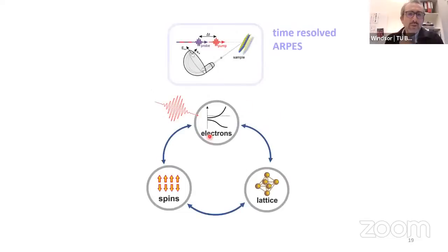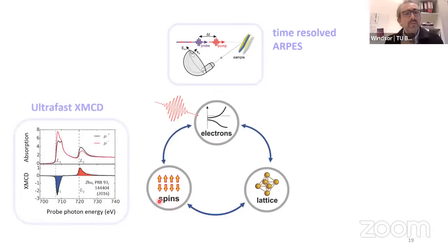Now, after I'm done looking at electrons, I'm going to look at the spin system. To do this, I'm going to use XMCD. I'm not going to describe XMCD in so much detail, but you can see here a paper about XMCD on FGT from 2016. The key feature here is that we have two curves which represent absorption from left and right circular light. Because there's a difference between them, this difference shown here is proportional to magnetization. So this is what we're going to do.